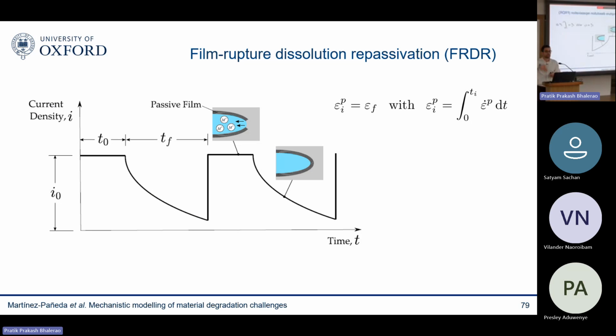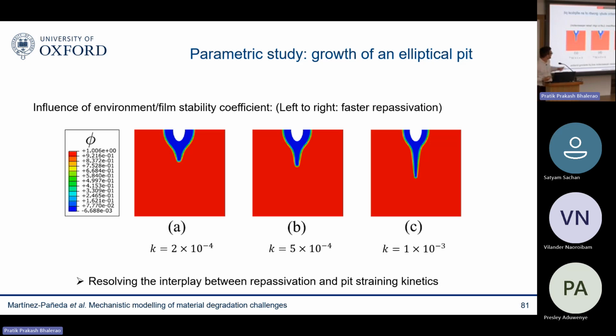There's also the film rupture mechanism process. I'm not going to have time to explain it, but those of you familiar know that mechanical fields will rupture the passivated film that prevents some metals from corroding, like stainless steel. So we are able to capture this. You can solve for a mechanical problem as well, and you can accumulate strains and decide when the film is ruptured. And when you do that, you see this pit to crack transition phenomena. You can capture very well this interplay between repassivation and straining kinetics.